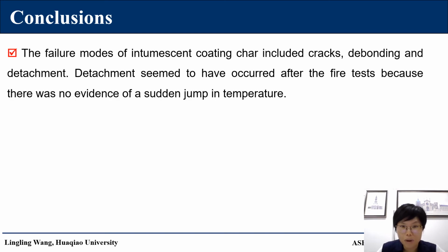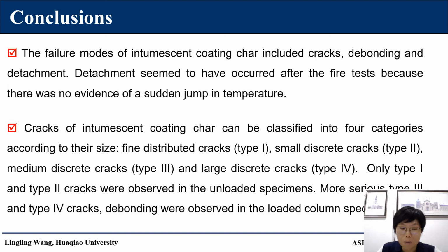Okay, conclusions. The failure modes of intumescent coating included cracks, debonding, and detachment. Detachment seemed to have occurred after the fire tests. Only type 1 and type 2 cracks were observed in the unloaded specimens. More serious failures were observed in the loaded column specimens.